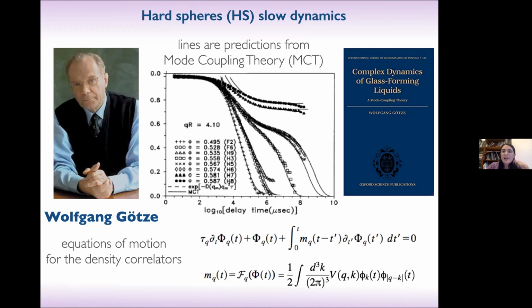Mode coupling theory is a theory for the equation of motion of the density correlators, and equivalently of the mean-square displacement, which, as I showed you up to now, are the observables you have to look at if you want to monitor the glass transition. So you have this arrest transition that happens. Through mode coupling theory, you can write an equation of motion for the density correlator, phi of Q. This equation of motion contains an integral term; it's an integro-differential equation.